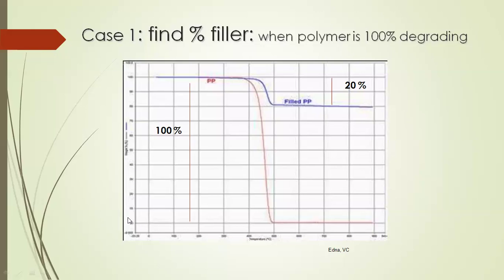Whatever residue is remaining is 0%. Then do a TGA of a base polymer and do a TGA of your filled polymer. See, my filled polymer is giving me 80% residue and only 20% weight loss. What does it tell me? The curve is telling me that in my sample, how much filler is there? Can anyone tell me? Because the material is 100%